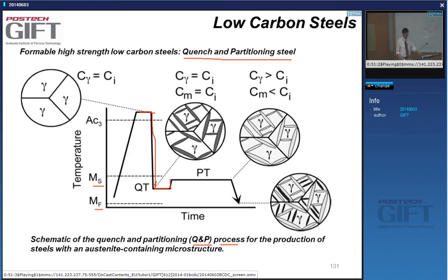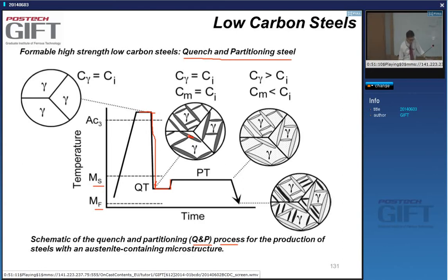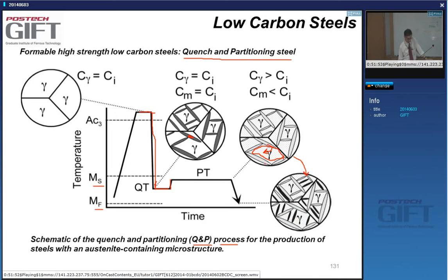The next step is to reheat this microstructure. The martensite, which is supersaturated in carbon, will transfer the carbon into the adjacent austenite. When this happens the MS temperature drops, so that when you cool down, some of this austenite is retained — it will not fully transform to martensite. You are left with a microstructure that is martensitic with pockets of retained austenite. This carbon transfer happens very quickly — matter of seconds — because in this partially martensitic microstructure the diffusion distances are very small.